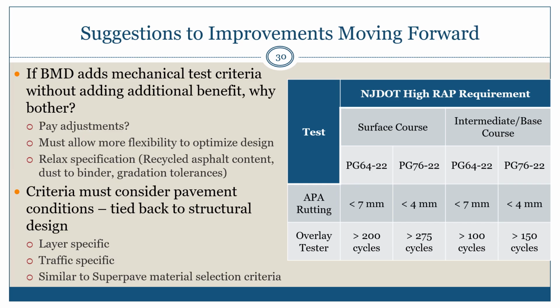Also needs to consider that we must be more flexible in our design and specification process if we're going to try to optimize a design. Looking at possibly relaxing specifications on RAP content, dust to effective binder, gradation tolerances. As long as the mix meets the rutting and the cracking criteria established by the state agency, then some of those specification constraints that are currently applied should be relaxed or even removed in lieu of confidence in the performance